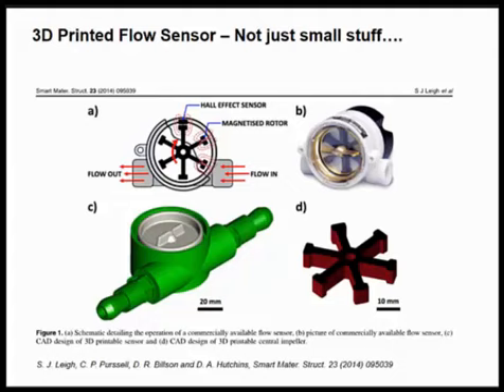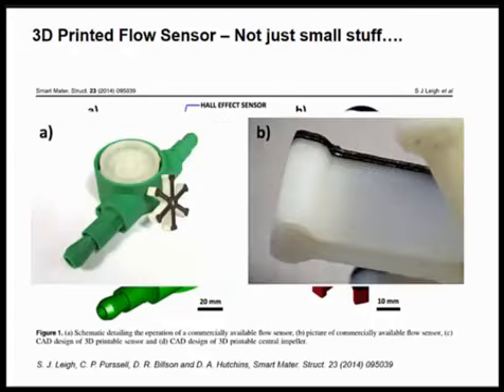We copied this design, or imitated this design, and made our own impeller. Rather than make the whole of the impeller from the magnetite material, we just did two layers, so about 200 microns on top. The rest was thermoplastic and then just two layers of this functional material. So you can see the layers on top of the impeller. So, a fairly simple device.